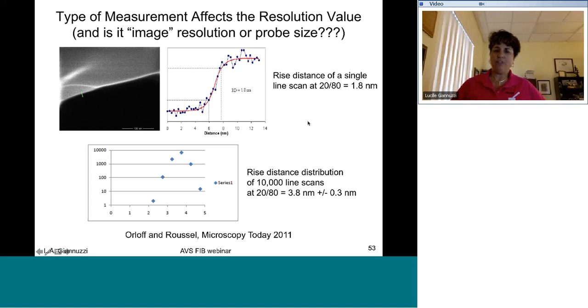So, again, you have to ask your vendors, how are they measuring the imaging resolution? What sort of statistics are they using? Is this just the best line that they're measuring, or is this over several different lines? And so, again, if you look at the rise distance distribution, 10,000 line scans at 20/80, you get 3.8 nanometers plus or minus 0.3 in this particular example. Whereas this single one might be just the best, and you can actually get a better number depending upon what you're measuring. So just be aware of that when you're measuring imaging resolution with the FIB, how they're doing it and what's actually being done.